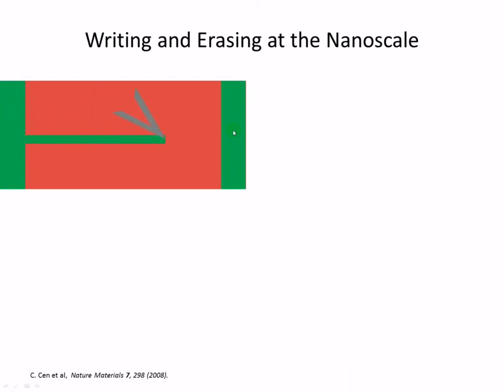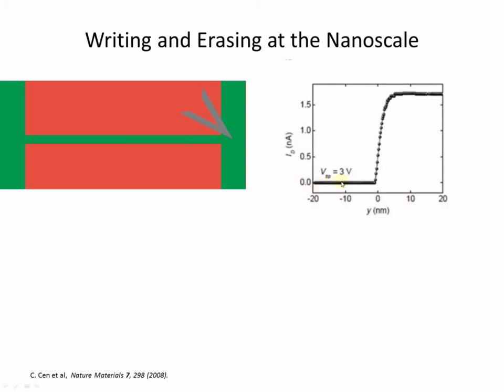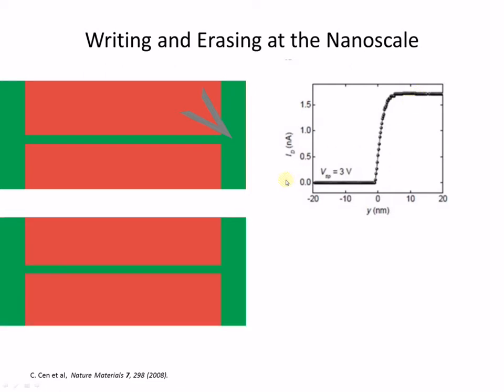What we can do then is take an AFM probe and apply a positive voltage to this and move it across the surface, and when it does, it locally switches the interface from the red insulating phase to the green conducting phase, creating a wire. And we can monitor the conductance, or the current, if we apply a small voltage, as we move this across, and we find that when we complete a circuit, we see that the current jumps up. Now, just like the Etch-a-Sketch, we can then take this structure, and instead of applying a positive voltage, we can apply a negative voltage and move across the wire.